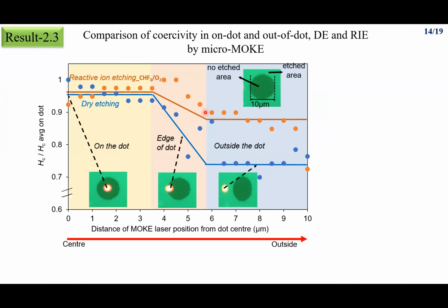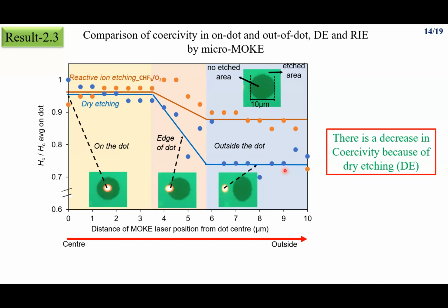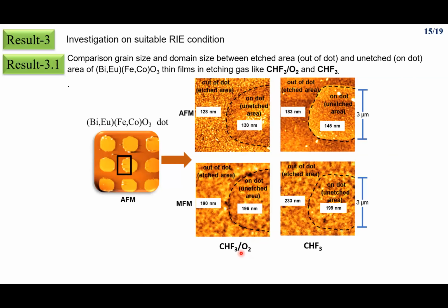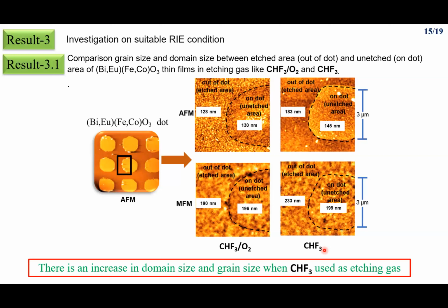To confirm it again, I checked the change in coercivity, and I found in the case of dry etching, there is a drastic change in the coercivity, and this is studied by the micro-MOKE measurement system. Here also I found that dry etching is giving more magnetic damage, and that RIE is not giving magnetic damage. Then I found that in the case of reactive ion etching with oxygen, there is very small change in the grain size and domain size, but in the case of without oxygen, there is a change in the grain size and domain size.